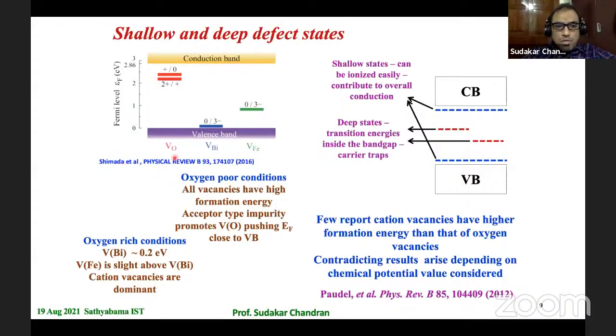And of course, you can also have cationic vacancies like I showed in the first picture, where the vacancy of bismuth and vacancy of iron reside close to the valence band. They are acceptor dopants. So depending on the concentration of what kind of defects you have, the properties would change a lot. In any case, the states that are pretty close to the conduction band or valence band, the donor and acceptor states, can contribute to the overall conduction with a little energy, and therefore it's going to modify the electrical properties of the material a lot.